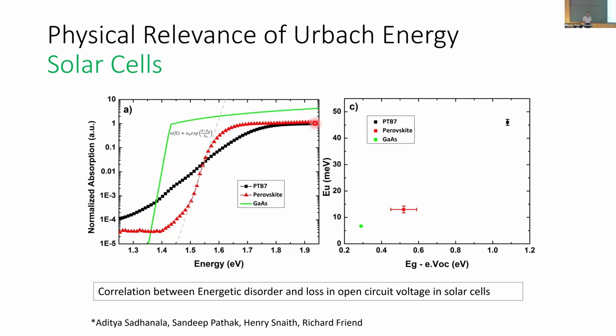So if you measure the absorption for these three, you can easily say that gallium arsenide has the sharpest drop in absorption, so it is less defective, which we already know. If you look at the organic semiconductor, the tail drops in a shallow manner, meaning more defects. Perovskite is somewhere in between.